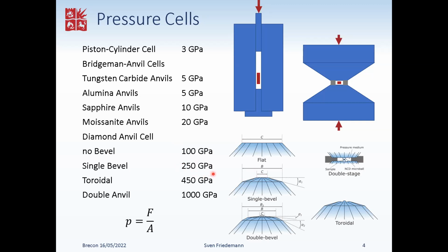If one wants to go beyond this, one has to shape the anvils in a toroidal fashion, that's indicated here, because at high pressures, the diamonds themselves start to deform, and this essentially anticipates the deformation that's going to happen and counteracts that, and hence increases the strength of the diamonds at high pressures. Limit for toroidal type cells is about 450 GPa.